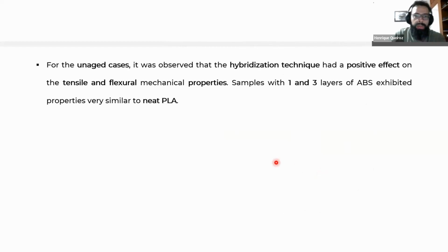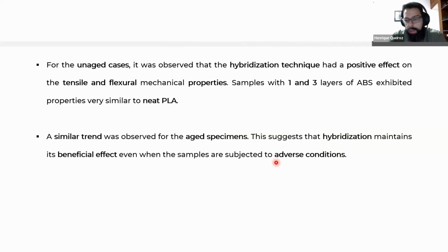And so our general conclusions here is that the hybridization technique, which is to use different materials in the same specimen, was positive, right? It helped maintain some tensile and flexural properties. For example, the 1 and 3 layers of the ABS maintain their properties pretty near the neat PLA. And we also saw a similar trend for the aged specimens as well. This suggests that in general, this idea that hybridizing PLA with ABS for marine applications is viable and it can be used.